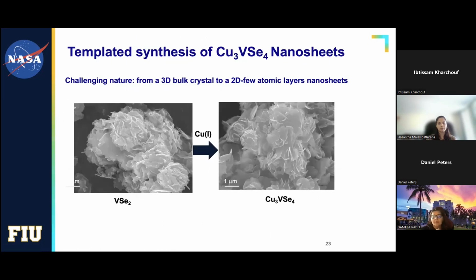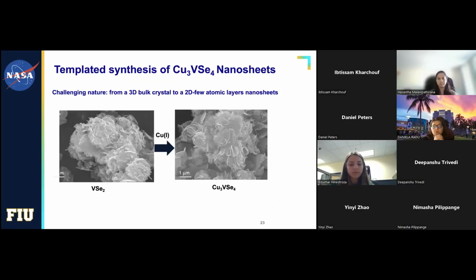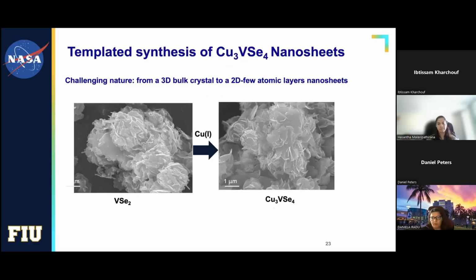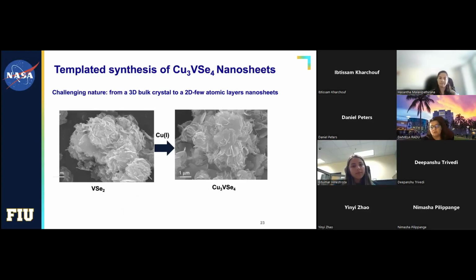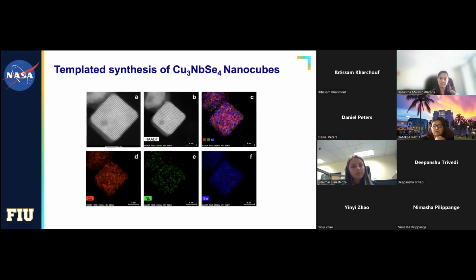But again, there is the fascination of working in the two-dimensional realm, right? It's great. So we are recently looking into how to create solar cells with copper vanadium selenide in 2D. And what is most interesting about this material is that it should not form nanosheets. So again, it's a miracle at the nanoscale that this material can crystallize in a quasi-2D morphology. On the other hand, the immediate neighbor, the niobium compound, forms nanocubes and does not form these nanosheets. And this is really a puzzling question that we are looking at.